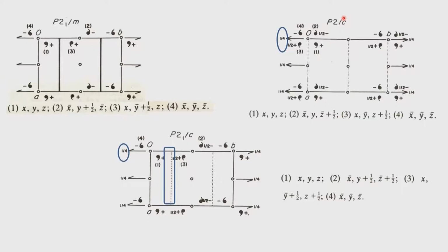So, if someone gives you the space group, in principle you should be able to automatically find the crystal system. You not only find the crystal system, of course, the moment you see the lattice identification, you see the Bravais lattice that is associated with it. Examine the symmetry that is given here and convert it to a point group symmetry. Suppose you are given 2 by C, the corresponding point group will be, with no translation involved, 2 by M. So, it is a centrosymmetric space group, and we conclude that it is a 2 by M point group. We have the primitive lattice, and therefore, this is a monoclinic system.